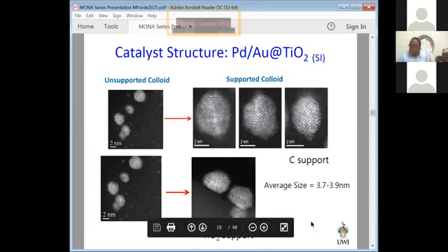When you put it on titania, you can see that now part of the spherical particle becomes truncated. And you can see over here, there's some interaction between the particle and the surface. And this interaction is, of course, much better than the interaction of the particle with the carbon surface. The sizes are about the same. I mean, this one is a little larger in the titania example, but the composition is the same in that the particles have both gold and palladium in them. And you can do an EDAX analysis to support that.